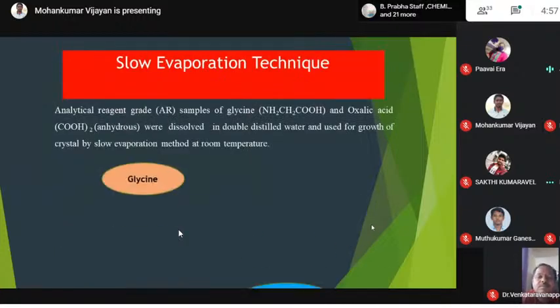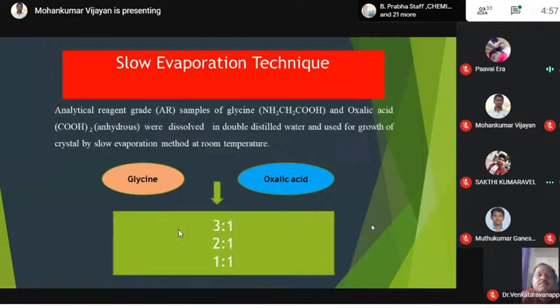Slow evaporation technique. This is the most successful method for crystal growth. In this method, the component can be dissolved in a solvent and left for slow evaporation, and slow evaporation can be done under atmospheric condition. Here we can see glycine is one of the components, and oxalic acid. They are mixed in 3 different ratios, 3:1, 2:1 and 1:1.